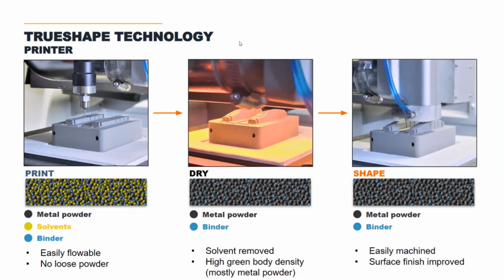And we come in and we actually machine the material. So this is why we're able to achieve those very, very crisp features, excellent surface finish, because we're actually machining it during the printing process, every single layer. It's very soft at this stage, so it's very, very easy to machine. We refine the finish, and we can actually incorporate some features that we wouldn't have been able to print initially because of the printing process.